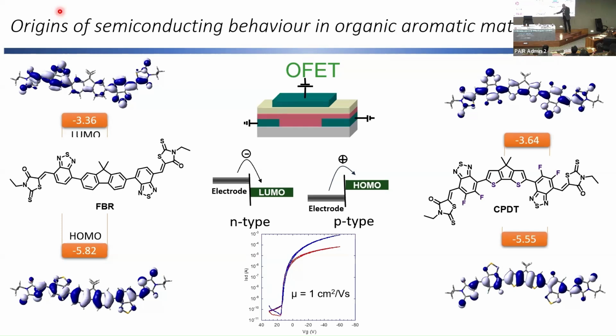And if we look at what's called a transfer characteristic, so this is the key electrical characteristic of a transistor. You can see that the current that flows between the source and the drain here as a function of the gate voltage has this type of shape. So if this was a resistor, it would just be a linear shape. But you can see that by changing the gate voltage here by only maybe 1 or 2 volts, our current increases by 1, 2, 3, 4, 5 decades. So 5 orders of magnitude.